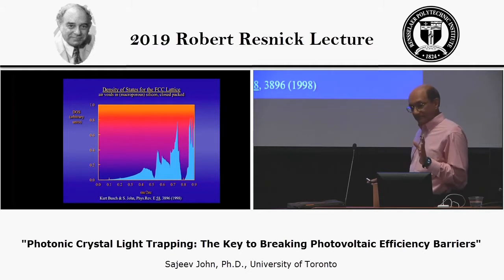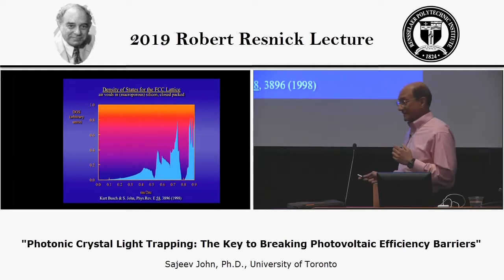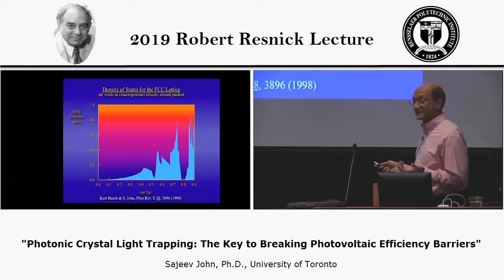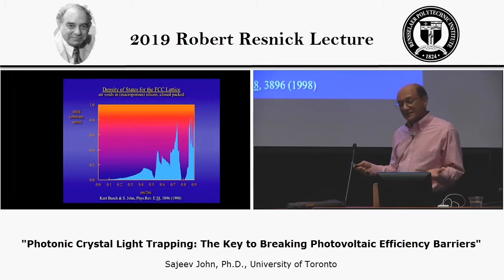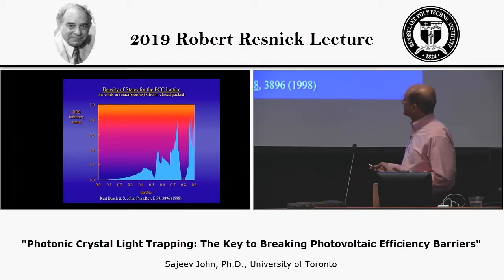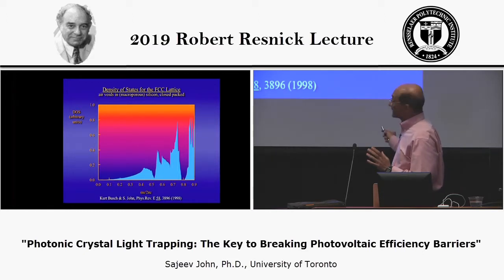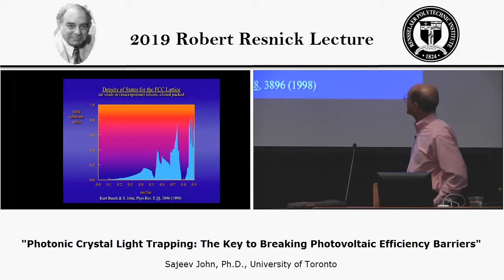Another feature of that photonic crystal that I just showed you is how it changes the electromagnetic density of states. If I just had a homogeneous medium, the electromagnetic density of states, the number of modes per unit frequency interval, would simply be a parabolic curve without any specific features associated with it. This photonic crystal has certain regions where the density of states is much lower than that, and in this part of the spectrum, this is the complete photonic band gap, no modes whatsoever. But in addition to that, there are regions where the electromagnetic mode density becomes much higher than would happen in a uniform or homogeneous medium.